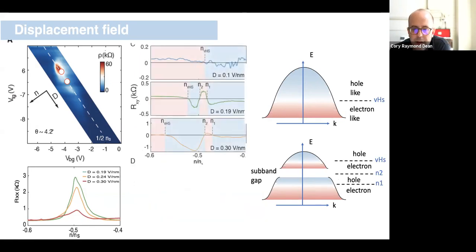Okay, so let's go back to our data. Now I'm looking at line cuts of the Hall resistance here. And indeed, what we see is that as a function of displacement field, we observe a transition that looks exactly like this cartoon picture that I painted.